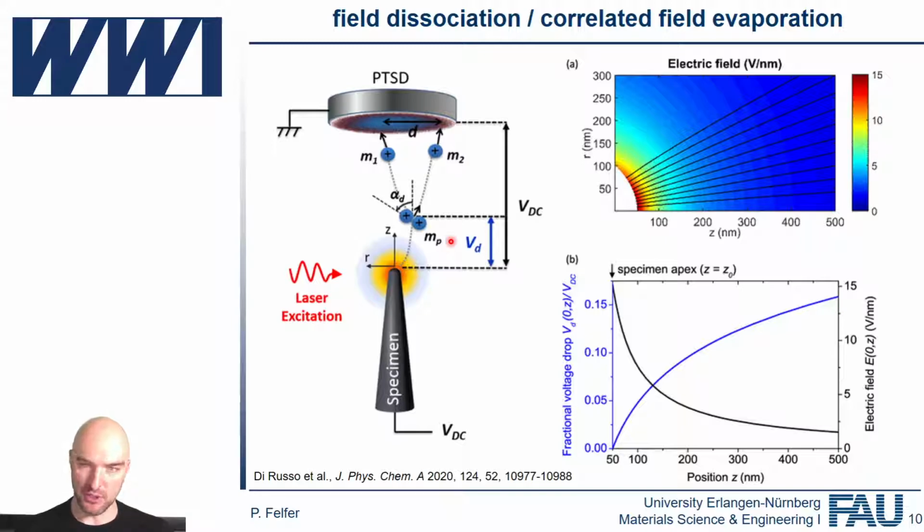The thing about those molecules is, a single atomic ion cannot fall apart. It can lose more electrons, but the ion is still an ion. It's just higher charged. If you have a molecular ion, say, we've had gallium nitride before, so you can get a gallium nitride ion that can fall apart. If you remove electrons, it can fall apart. And this is actually observed. So you can have an ion moving up to a certain point and then splitting up and maybe, but not necessarily, lose an electron.